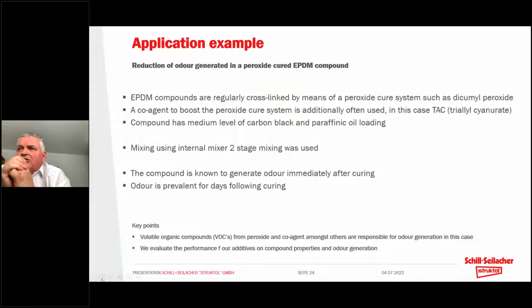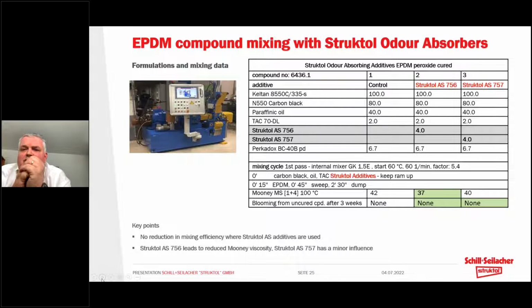So with next now, please, I'll jump into what we did with the additives and the numbers that we could measure. So this is our formulation. We have the EPDM, we have a normal, in fact, even quite low level of carbon black and paraffinic oil, the TAC and the peroxide, the co-agent and the peroxide. So a very simple formulation. And then we test the two different additives, the pastille product, if you like, the lubricant product, and the powder product, the inorganic or the dual action product.